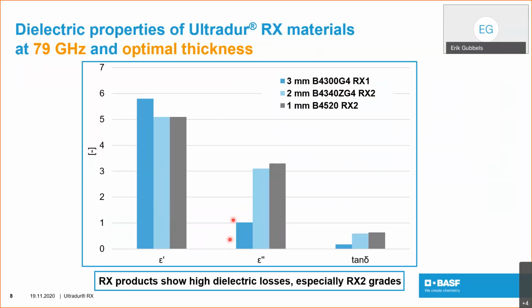You can see that already for the first generation absorber, we reach a dielectric loss value of 1, and the second generation even reaches values around 3, showing their capability of being absorbers. The dielectric constant increases to about 5.8, or around 5 for the second generation materials, showing that they're not too high to create a very high reflection, which would happen if you increase the dielectric permittivity too much.